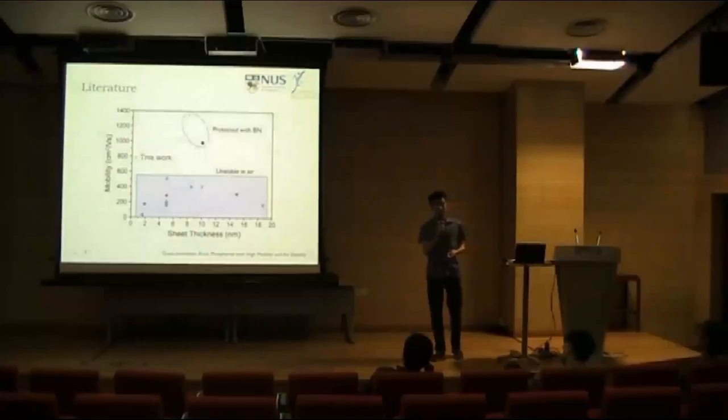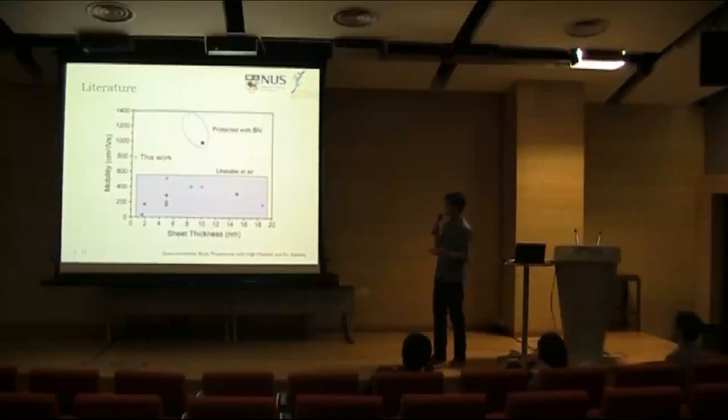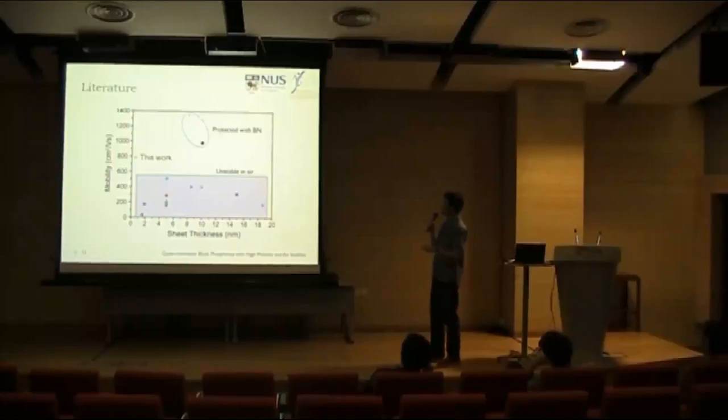And then we take a look at how our devices fare in comparison with the other black phosphorus devices. So we can see that we have actually fabricated the thinnest effective sheet thickness black phosphorus devices. And the mobility is also relatively high, and we are the only one that report on the highly stable black phosphorus devices without the need for encapsulation. So the thing about encapsulation using another 2D material is that this method is not scalable, so it cannot be commercialized.